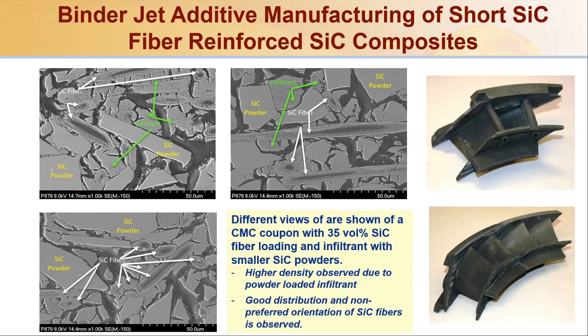So in this slide, you can see different views of a CMC coupon, which had roughly 35 volume percent silicon carbide fiber loading. And it was infiltrated multiple times with smaller silicon carbide powders as well as SMP-10. And you see there are different constituents there. There is, of course, the original silicon carbide powder. There is a fiber there. There is silicon carbide produced by the infiltration process. So there are some added materials. So that basically gives you the complexity of the microstructure, which you can get while densifying these parts. On the right side, there are some parts which were made using these types of compositions.